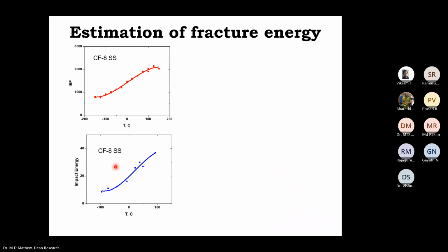And this curve represents the data obtained from standard impact tests, CVIT, using Charpy specimens by carrying out tests roughly in the same temperature range. You find that the shape of the curve is similar. Yes, the values are not comparable. For example, here we have values in the order of 1000, 2000, whereas here we have values in the tens. So values are not comparable, but the shape is comparable, which would mean even the DBTT can be determined from this graph. So just by doing ball indentation tests on one sample material, you will be able to get an estimate of the ductile to brittle transition temperature.